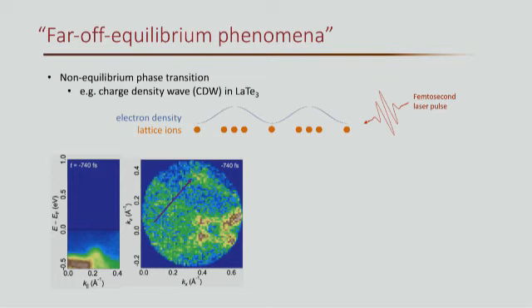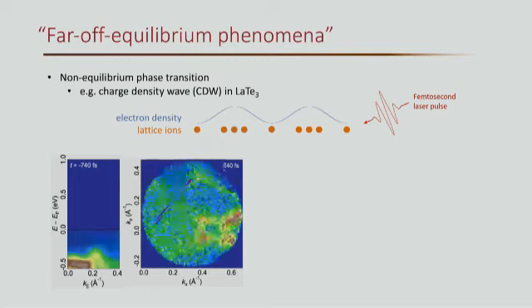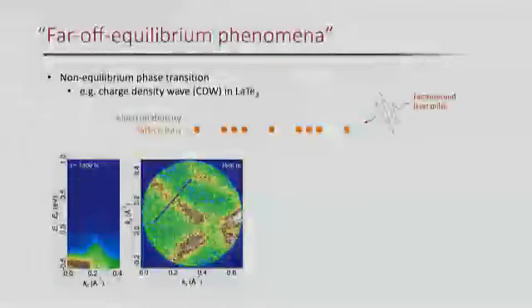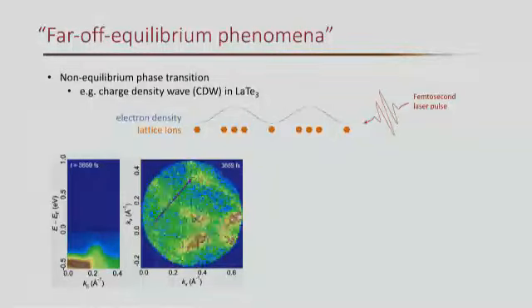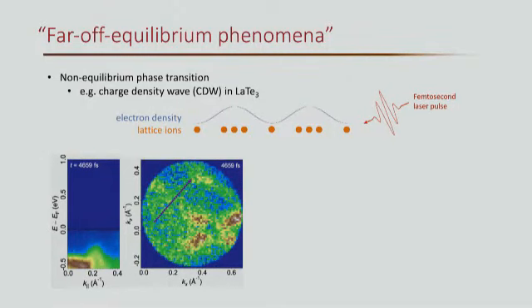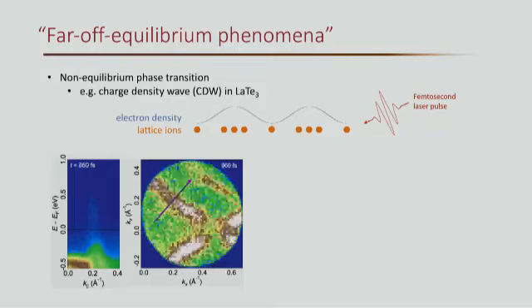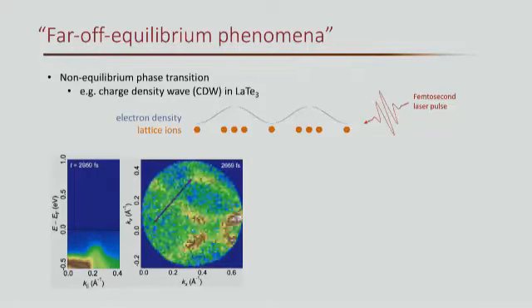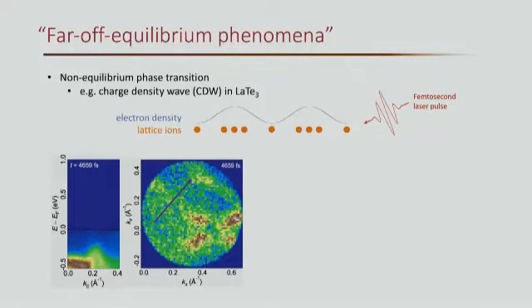It's almost 400 meV. So as we pump the system, we can see there's a partial suppression of the gap. And if we look at the Fermi surface map, you can see a partial closure of the Fermi surface as well when the light is incident on the sample. I'm going to go into more detail to explain this movie later, but here's a kind of zeroth order observation. So the TARPES is measuring the electronic response.